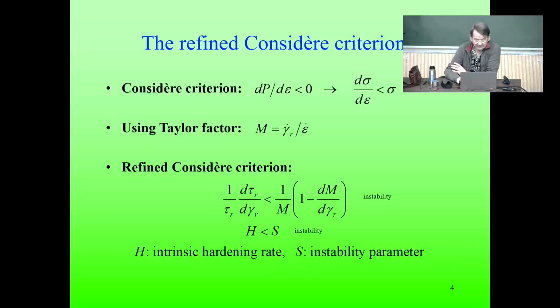So the Consider criterion is simply when you are looking into the hardening rate of the material during tensile testing. So the derivative of the flow stress, which is modulus, if it is less than the stress level itself, then deformation is localizing, and then the sample breaks. So this is a very simple equation, and with the